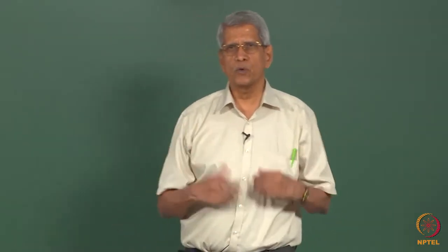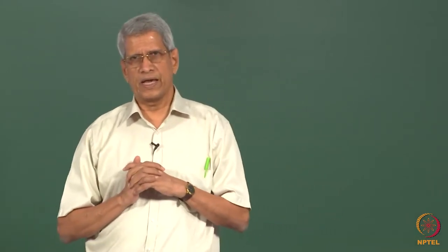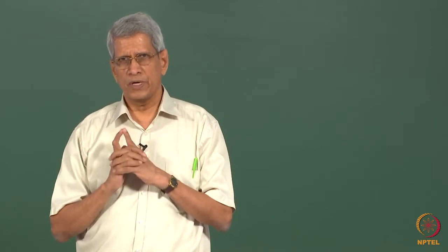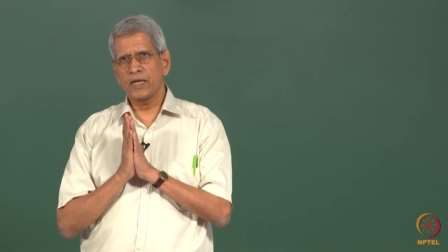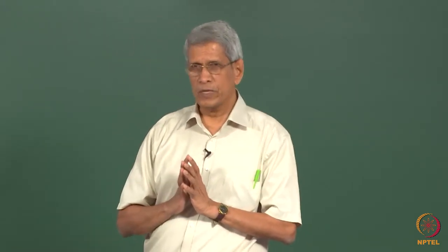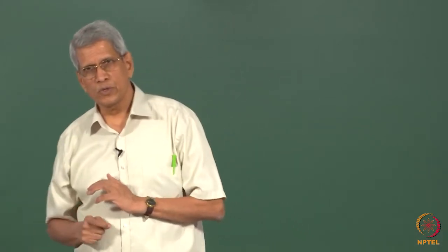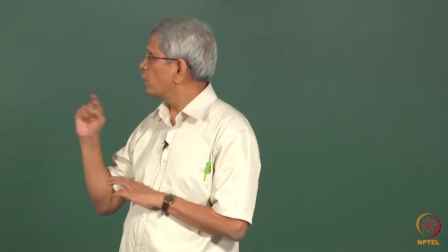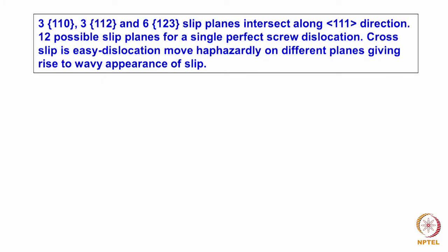Let us look at any particular specific 111 direction. That direction can be contained by 3 110 type planes, then 3 112 type planes and 6 123 type slip planes. The common intersection of all of them could be a specific 111 direction. So if the dislocation is a screw dislocation, it can easily cross slip from one plane to the other without any problem. Cross slip becomes very easy. It will merely move from one plane to another depending upon the way in which the maximum critical resolved shear stress is there.